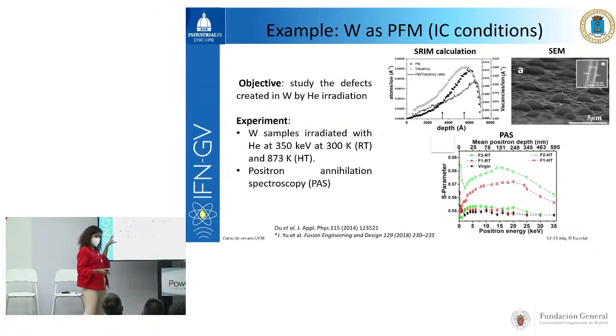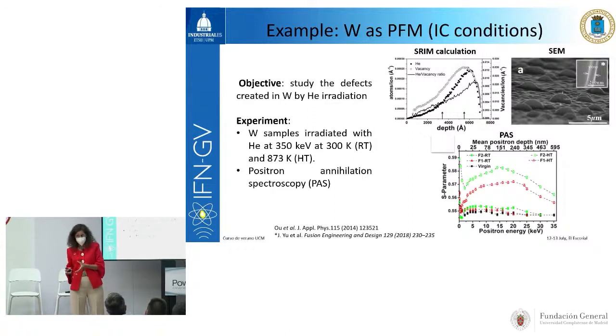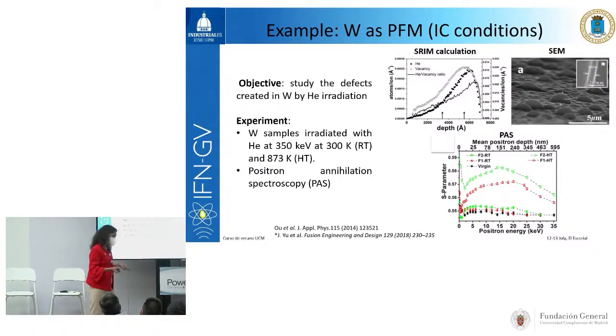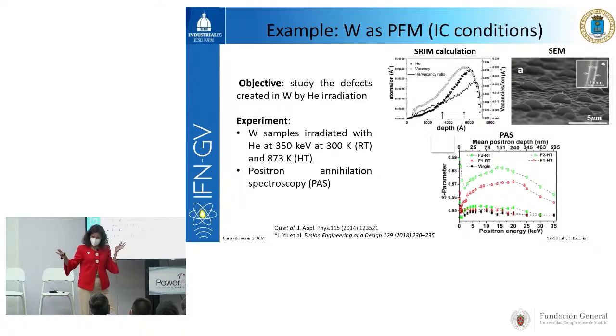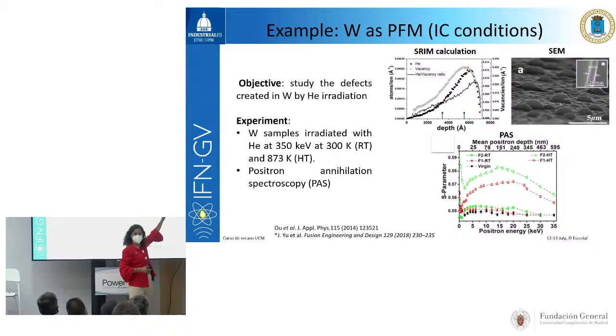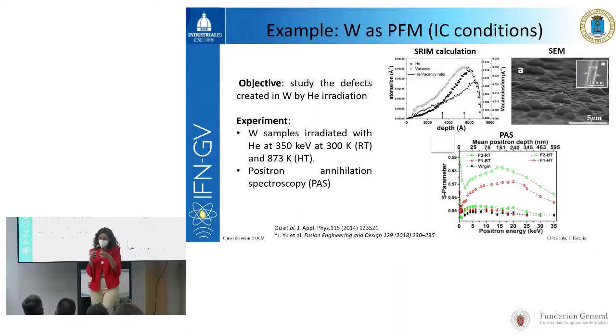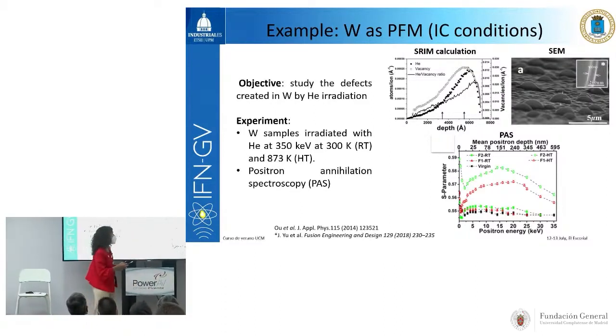Then this is another example. In this particular case, the tungsten was studied not under magnetic fusion conditions, but under inertial fusion conditions, not pulse, but high energy ions, 350 keV, and we observe a very different behavior. Remember, the radiation damage depends on the radiation conditions. Here we use the same ion, helium, but a much lower energy. And then what we observe are some blisters on the sample surface, so helium has formed bubbles on the sample surface.